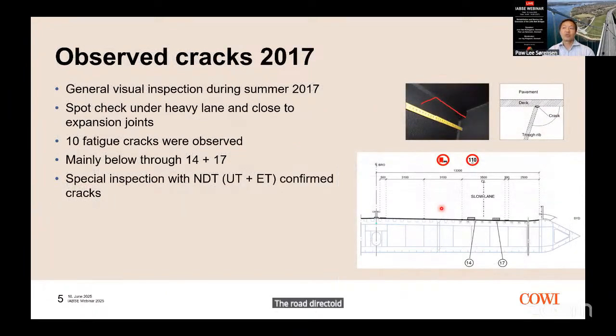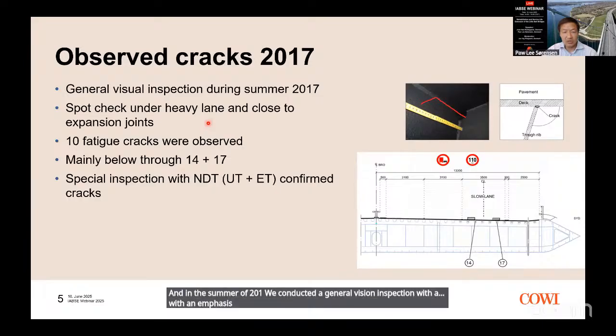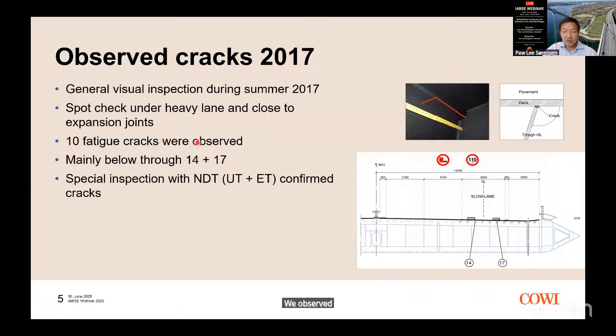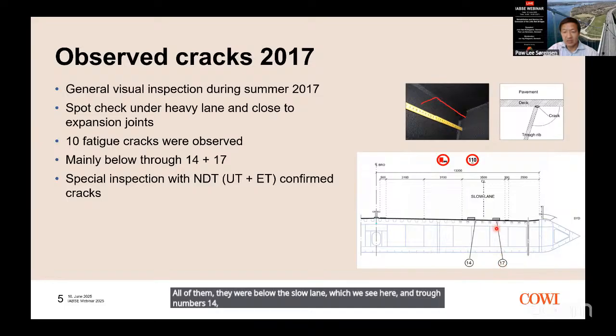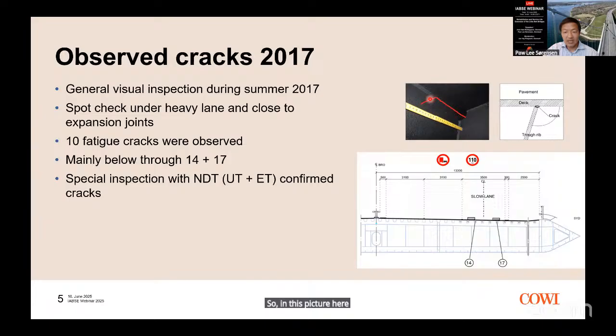The Road Directorate performs visual inspection typically every 5 or 6 years. And in the summer of 2017, we conducted a general visual inspection with an emphasis under the heavy lane and close to the expansion joints. We observed 10 fatigue cracks located in the weld between the trough and the deck plate. All of them were below the slow lane, which we see here, and trough numbers 14 and 17. So in this picture here, I've just highlighted the actual crack, but it extended quite far from the bulkhead, and then after around 20 centimeters or so, it moved down into the web of the trough.